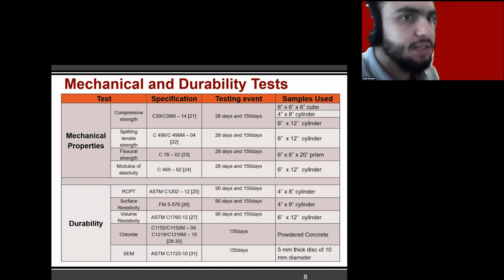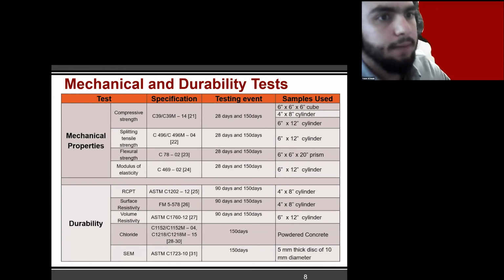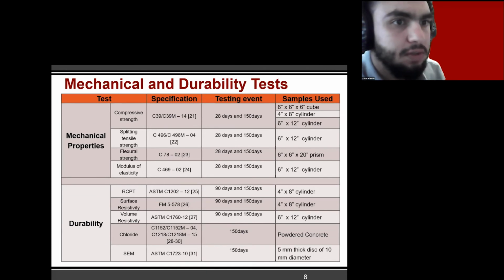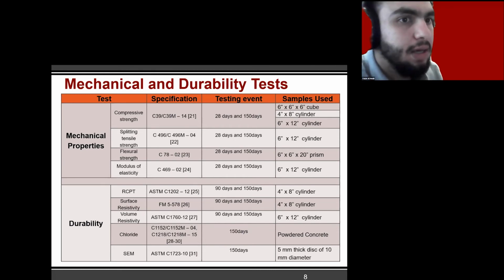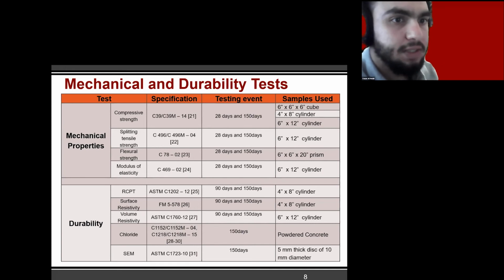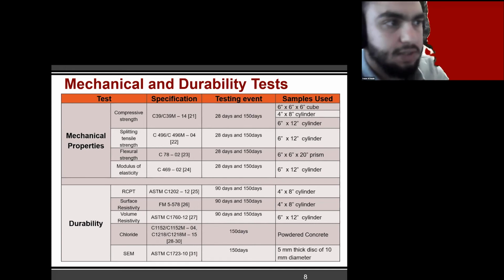Each of the 12 mixes produced enough samples for the mechanical and durability tests, where cubes and cylinders were cast for compressive test. Cylinders were used for the split tensile and modulus of elasticity test, and prisms were cast for flexural test. For the durability tests, mainly 4-inch by 8-inch and 6-inch by 12-inch cylinders were used on different tests, which include the surface resistivity, volume resistivity, chloride content, and RCPT, as well as the SEM.